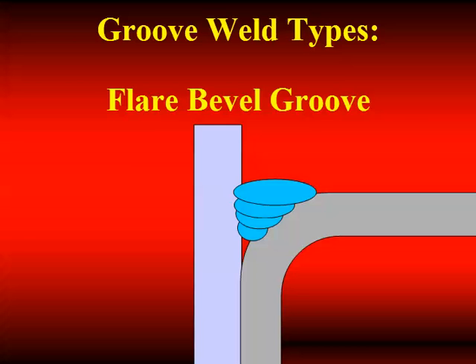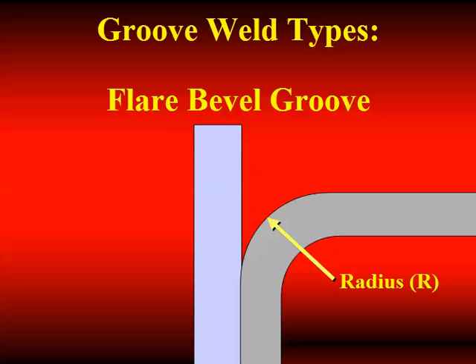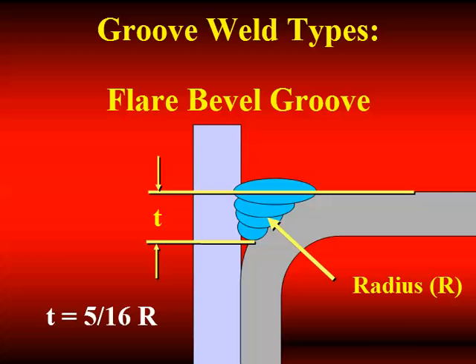Now, the throat is really a function of the radius, and the radius is a function of the thickness of the material and generally follows the pattern of being 2 times the thickness of the material. And what our code says, and this is an example, it's not always the case, I'll show you what it is. The code relates the throat that we get to the radius. And so in one example, the throat is 5/16 times that radius.